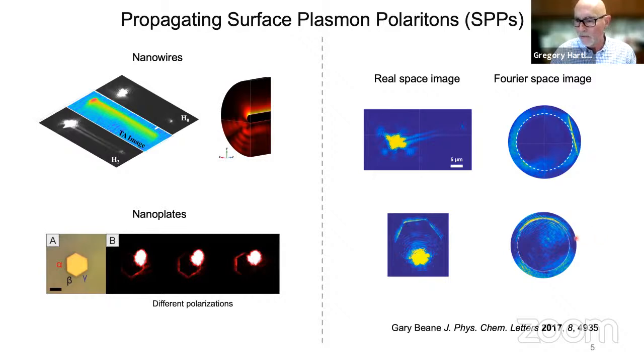For the plate here, you see an arc rather than a line, simply because you have plasmons moving off in different directions when you excite at the edge of a plate, and so you have a bunch of different wave vectors along here. In either case, you can measure the wave vector. Okay, and I'll show you how that gives you the lifetime information in a second. I just want to point out, though, that the propagation lengths are very sensitive to the thickness and the shape of the materials. So to do a proper study, one ought to have good control over those parameters.